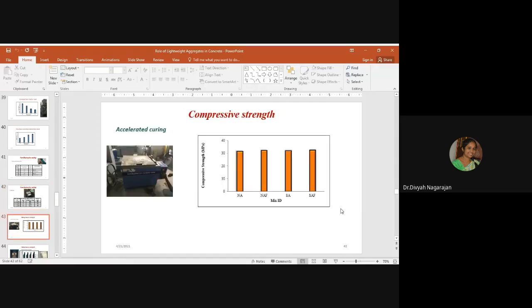Compressive strength. As I said earlier, the production or mix designing of the lightweight aggregate concrete was tedious, and it involved a lot of trial mix proportioning, and ANN and MATLAB tools were also used for proportioning of the concrete. Accelerated curing was also used as an indicator to find out the compressive strength of concrete. The accelerated curing tank was used, and water boiling method was adopted, and within 24 hours the compressive strength was estimated.